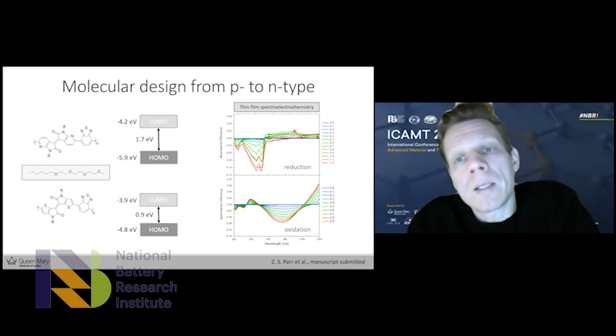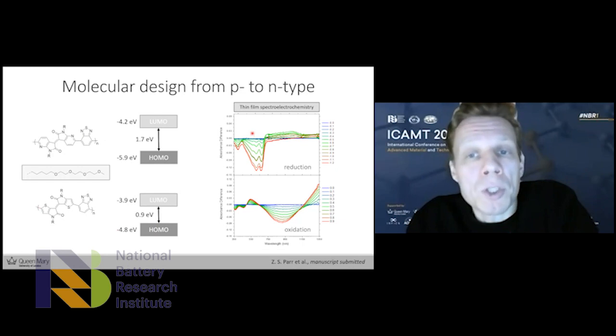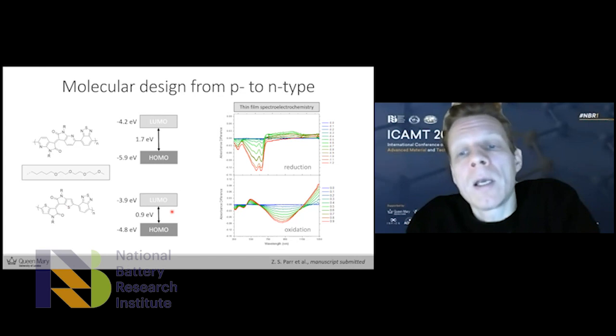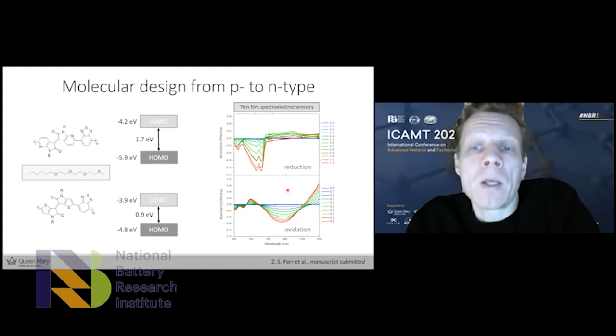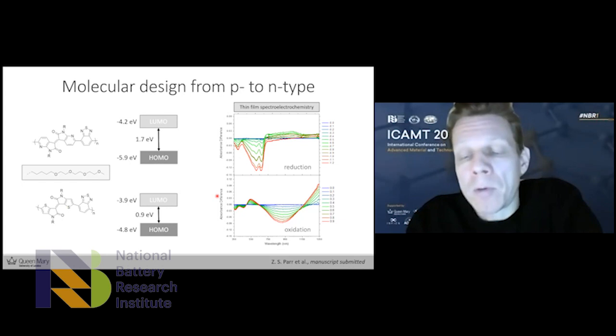We see that in the thin film spectroelectrochemistry. I'll go over this quickly, but when we do reduction of the aza isoindigo, we see a bleaching of the neutral state, and we see some indication of a negative polaron forming when we reduce this material. Similarly, when we oxidize the P-type candidate, we see a bleaching of the neutral, and we see the beginning of polarons forming out here in the near IR. So the spectroelectrochemistry in aqueous electrolyte is promising for this mixed conduction properties that I've been talking about today.